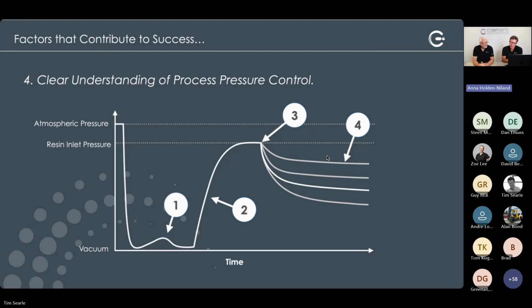Part 2 is where we have the initial resin inlet. It can be rate controlled, and we can build the resin set point and program that in, typically between 800 and 900 millibars. So that's our set point, and then number 3 is the end of the infusion.